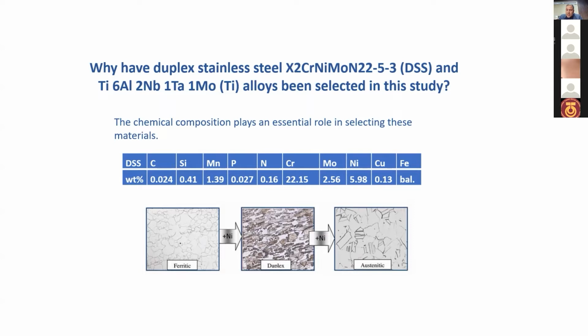Compared to the austenitic stainless steel, duplex stainless steel differs mainly in its chromium, nickel, and molybdenum content. Chromium is a ferrite former. At higher chromium content, more nickel is necessary to form the austenitic or duplex structure. This table indicates the presence of a high percentage of chromium, about 22%, that is responsible for the formation of chromium oxide, which protects the base alloy. Molybdenum contributes significantly to the stability of the oxide film, and the addition of nickel accelerates the cathodic reactions, while the addition of molybdenum retards the anodic process.